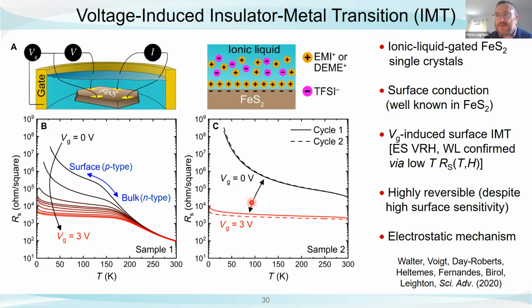Completely unlike the oxides, this is entirely volatile and entirely reversible. Everything points to this being a simple electrostatic induction of electrons. If you're interested in why it's so different than the oxides, please ask about that. That's something I think we have concrete ideas about, why pyrite responds so differently than the complex oxide materials. But the question here, of course, is when you drive that insulator-metal transition, do you see anything in the